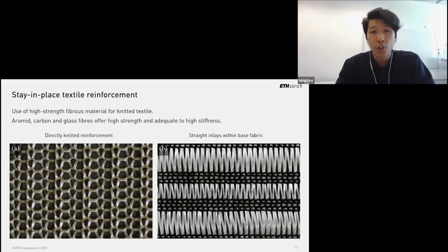One of the identified approaches from this study is a stay-in-place textile reinforcement system. Since the textile is already there as formwork, why not use it as reinforcement in the final state by utilizing high-strength fibrous materials? In this study, we distinguished between textiles where the high-strength material was used directly as yarn in the knitted fabric, as we can see on the left side. And on the other hand, the knitting machine also allows the integration of straight inlays within the base fabric. On the right side, you can see the white glass fiber rovings are just held by a black non-structural acrylic yarn.